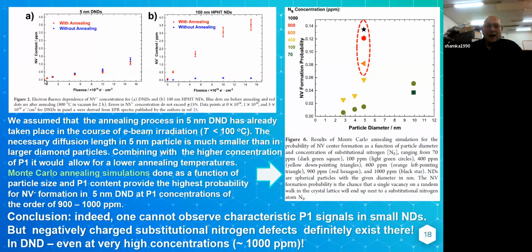Here you can see how the content of NV- centers changes in detonation nanodiamonds in comparison with 100 nanometer nanodiamonds. You increase fluence, you increase the number of NV- centers. This is well known. It is published in many articles. Olga and her colleagues published a lot of articles on this. But interestingly, for larger diamonds, you have to anneal the sample to get NV- centers. For nanodiamonds, you can compare, you don't need to anneal it. It appears. Maybe it's room temperature annealing. Okay, it is possible for small particles.